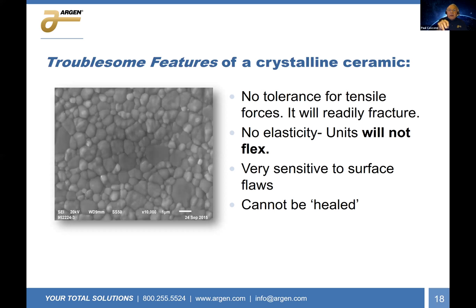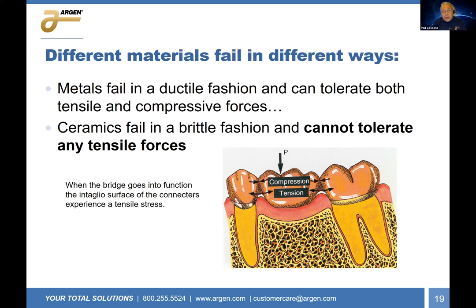Sometimes when you have a situation where you want to seat it, a PFM may flex and then seat itself again. Zirconia will just crack. It's very sensitive to any surface flaws, and it cannot be healed. Any crack in zirconia is just going to continue to go. When the crack starts, it travels at the speed of sound. So our small thin wall units don't have a chance to provide for any type of stopping of the crack.